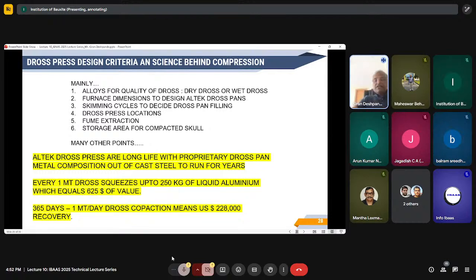Then fume extraction. Whether your dross press is near the common fume extraction or you need a separate fume extraction unit, which can be provided. And then there has to be a storage area for compacted skull. Now you don't get skull immediately. You have to take the pan out, put it for 1 hour cooling, topple it, and then they take the pan back to the furnace. So that has to be at a designated place, which should also be strategically located so that you can keep on stacking the skulls one on another. So there are many points.